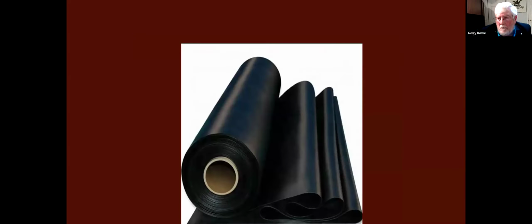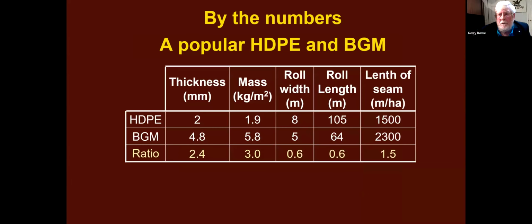So here is a roll of BGM. And what I did for this table is I went to the literature and I pulled out the data sheet for a commonly used HDPE and one for a BGM. It was a 2 millimeter HDPE with a mass of about 1.9 kilograms per square meter, a roll width of 8 meters, a roll length of 105 meters, and it's pretty simple math to calculate. That means you'll have about 1,500 meters of seam per hectare, just considering the ends and the edges of the rolls being seamed. And that's without any additional patches being considered.